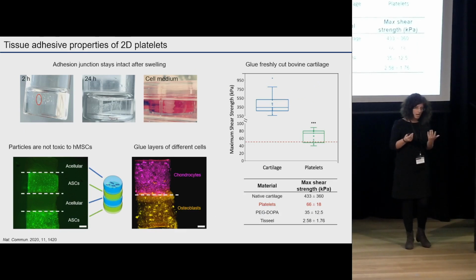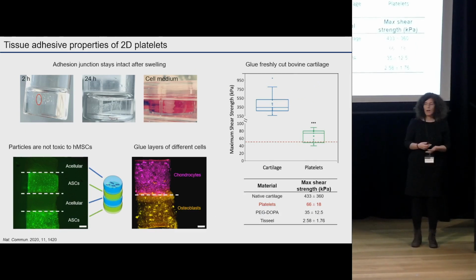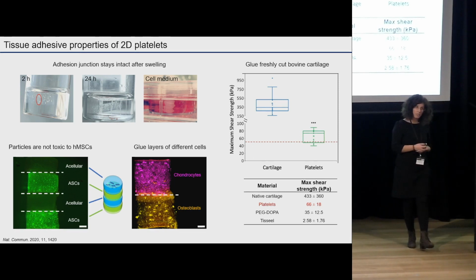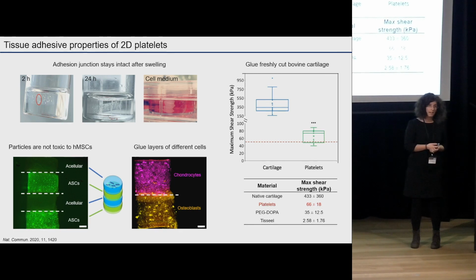The next thing is that we needed to prove that this adhesion was stable in wet environments. And as you can see here, it's actually stable in cell culture media as well for up to 2 weeks. So we observed no detachment of the hydrogel, and we also made constructs encapsulating cells in one layer with an acellular layer. So we built, again, our hydrogel with cellular and non-cellular layers. And then we glued together 2 different cell types, in this case, osteoblasts and chondrocytes. But we also found out that we could glue tissues together. And in this case, we tried with cartilage.